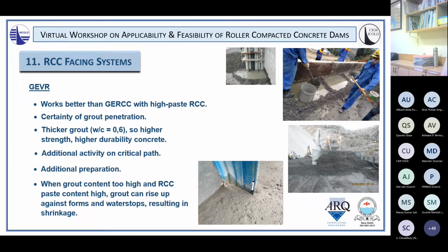When the RCC being used is too workable and has too high a paste content, grout can rise up against particular inserts into the RCC, such as water stops and the formwork, and this can result in a thin grout film against certain elements, which can then shrink and crack and can increase permeability. It's just a question of establishing the quantity of grout on the basis of what the particular RCC requires, not designing it for a particular number or volume of grout.